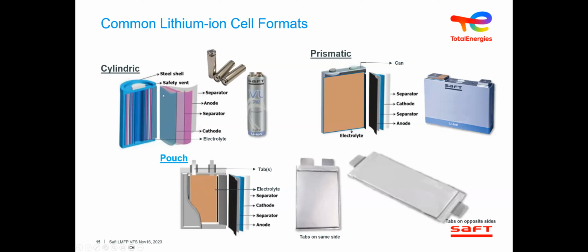But intuitively, on a cylinder and on a tube like that, you create zoning of temperatures, which is a challenge for this technology: how to extract the heat, as we saw prior with the thermal runaway. Extracting the heat and the stability of your SEI and your electrode is paramount. And so having a large cylindrical system is sometimes a challenge to extract heat. Plus, a circle is not ideal for integration, as side by side you have some waste. So prismatic is interesting. However, it creates more edges.